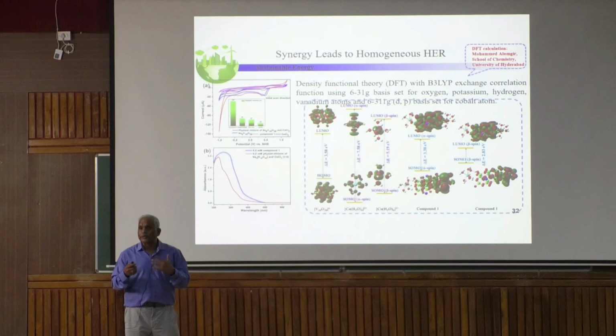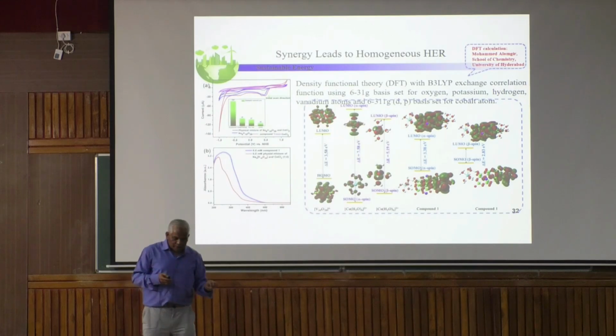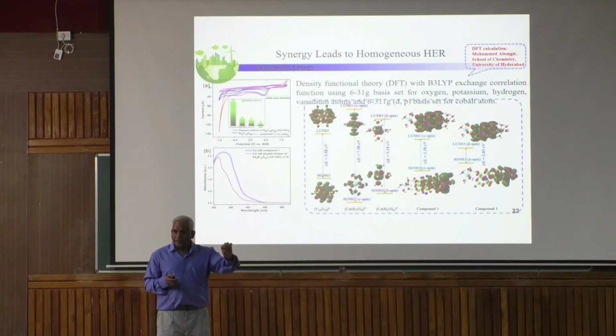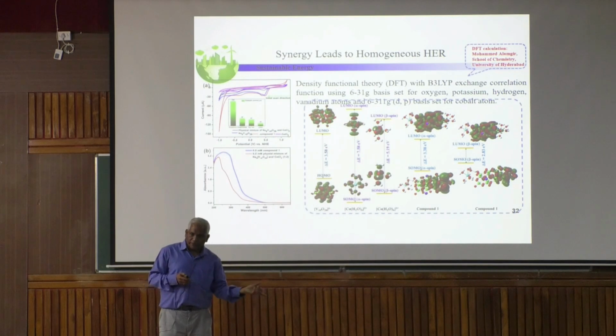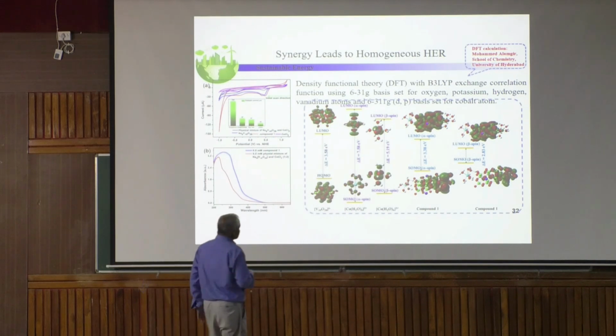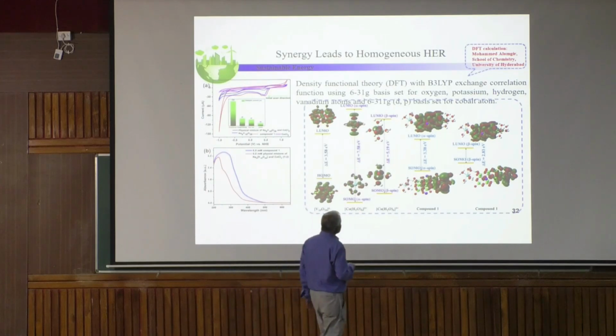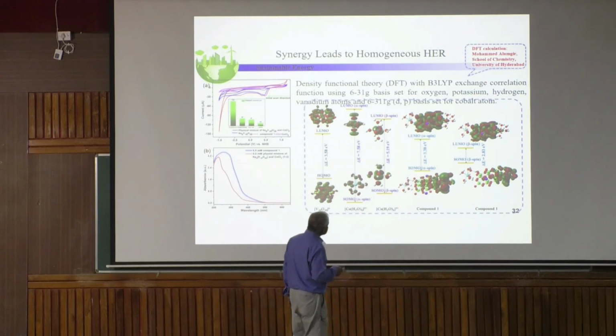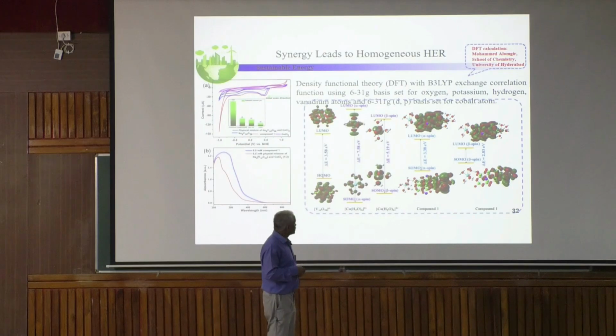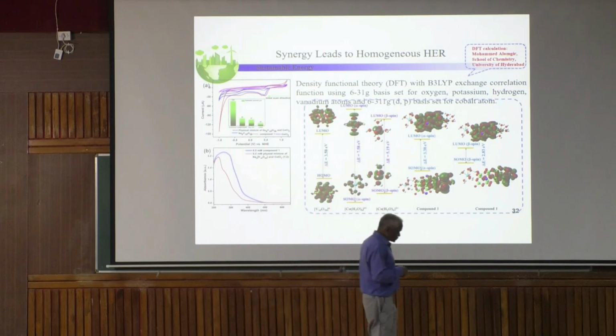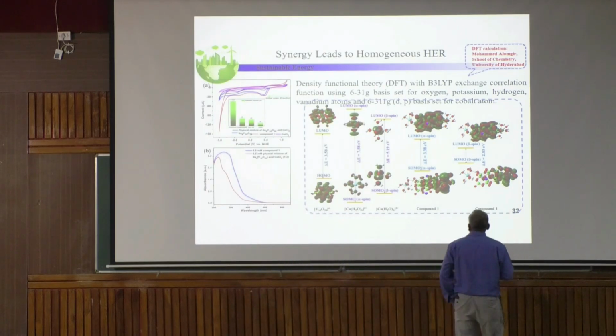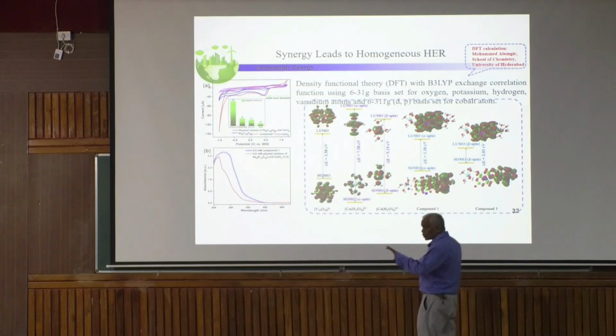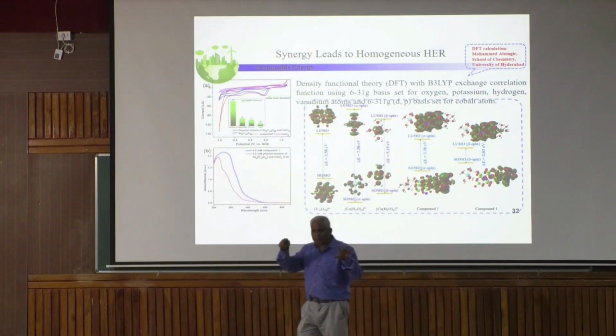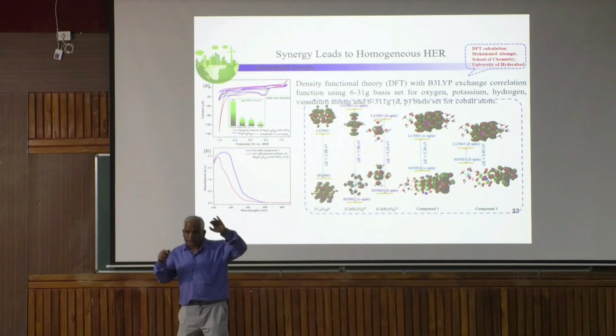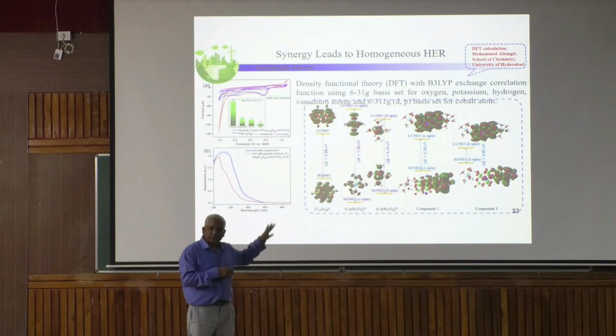Now, how it happens, I would like to tell you. In electrochemistry, the machine will give some electrons. The electron will be taken by what? Will the cluster take it first, or cobalt first? That you want to know. Now, we see that the LUMO is delocalized here, and the SOMO is singly occupied. So we found that in the case of the cluster, the LUMO is electronically occupied in line with the vanadium cluster. That means when the machine gives electrons, the vanadium will be reduced first.